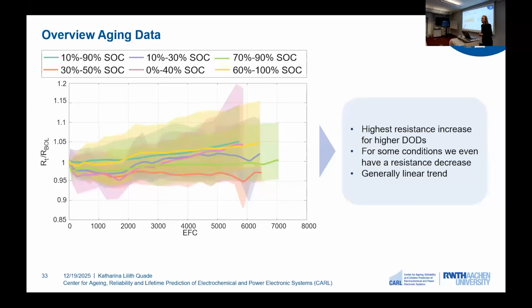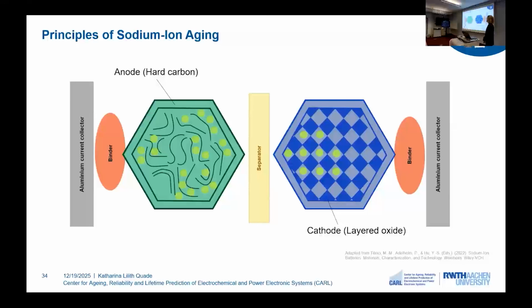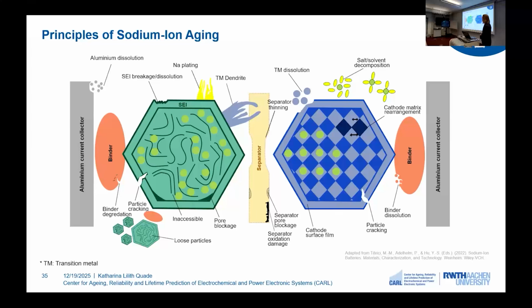And to understand this more, we need to have a look at the aging phenomena happening in a sodium-ion battery. And here you can see a schematic of a sodium-ion battery featuring a hard carbon anode and a layered oxide cathode. And you can see other typical components, the current collectors, the binder, and also the separator. And I will now include different aging phenomena and where they are happening. However, this will not be a fully comprehensive overview because even for lithium-ion batteries, we do not fully understand the aging phenomena happening in a cell, let alone for sodium-ion batteries.